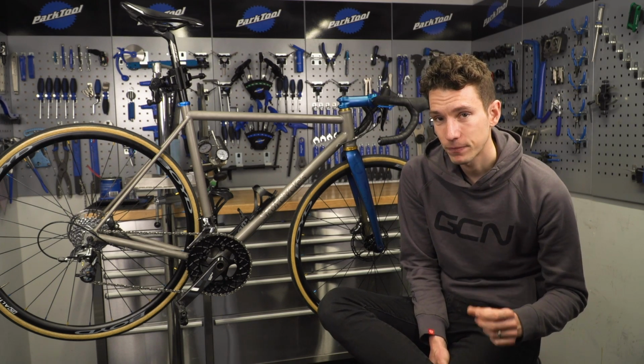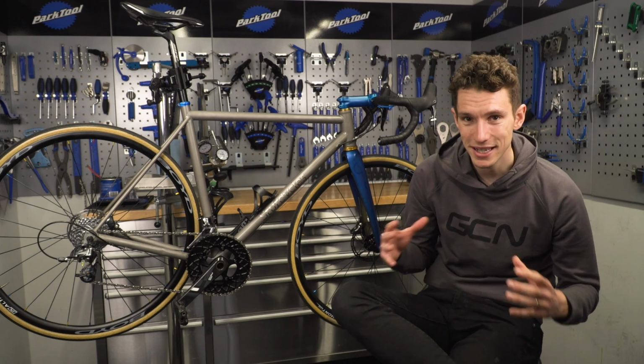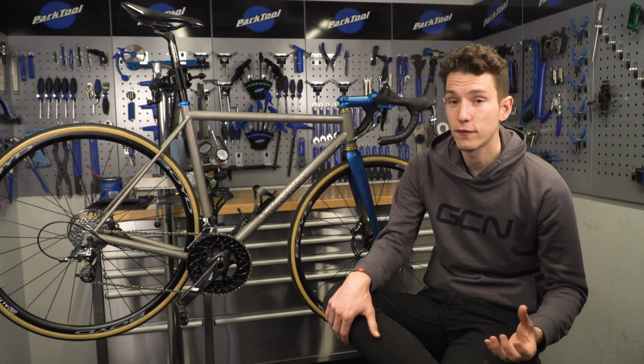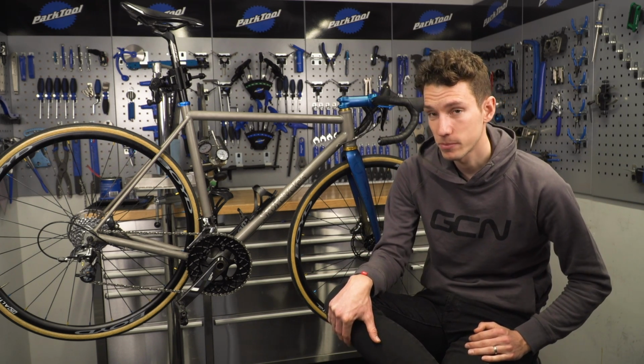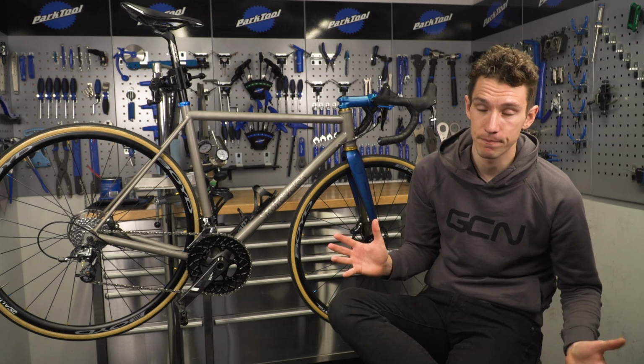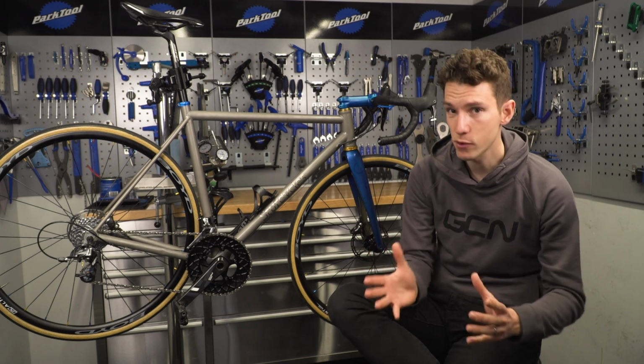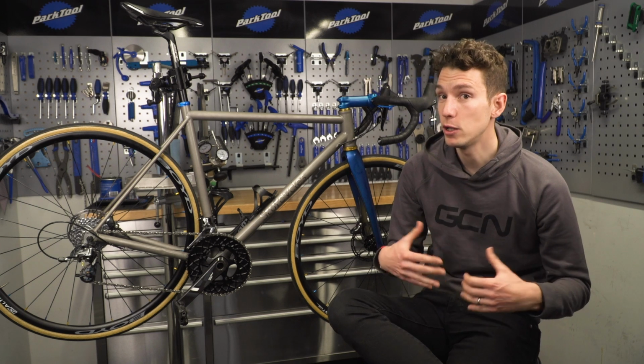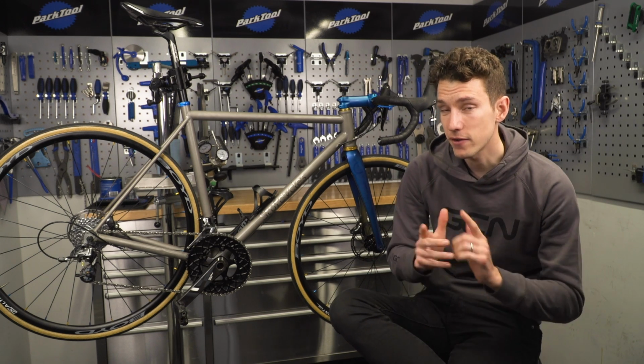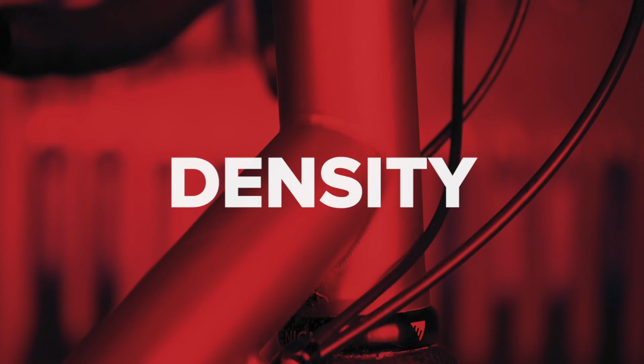And actually most 6,4 titanium tubes are rolled from sheet metal and then welded, whereas 3,2.5 tends to be seamless. And so that actually gives a more consistent overall tube, and therefore it's better from a quality control perspective. So in other words, basically, although on paper the material properties of 6,4 titanium might look better, it won't necessarily yield a better bike.